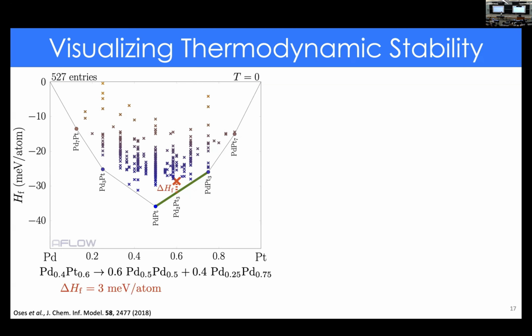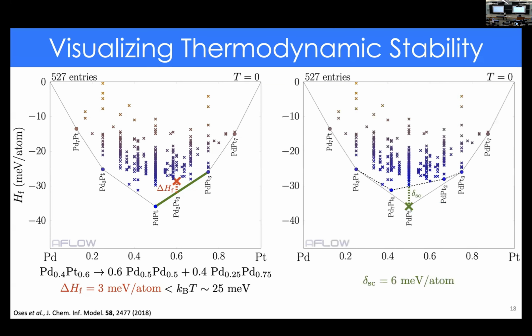This was an understanding that Gibbs had, and you could do these calculations very simply just from that distance on the y-axis. So we get 3 meV per atom. Is that big? Is that small? We have a threshold here that we generally define. We can compare it to room temperature excitation, which is about 25 meV. So we can say that this structure may form at room temperature. You can think of the 25 meV as an error bar that tells us what is likely to form at room temperature, even if it's not the most stable, because these calculations are performed at 0 temperature.